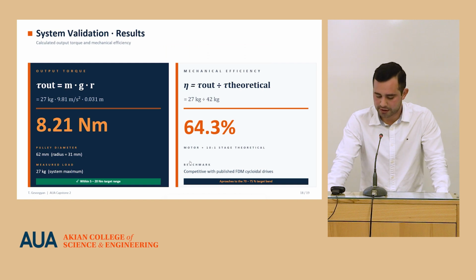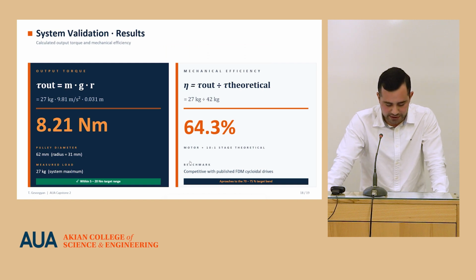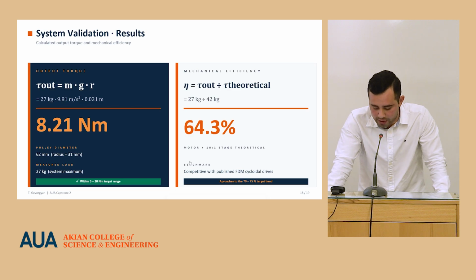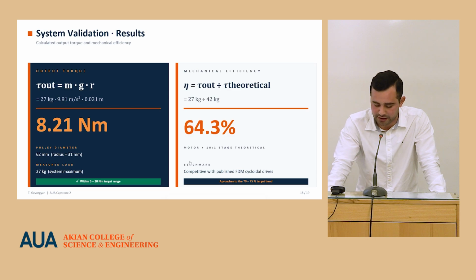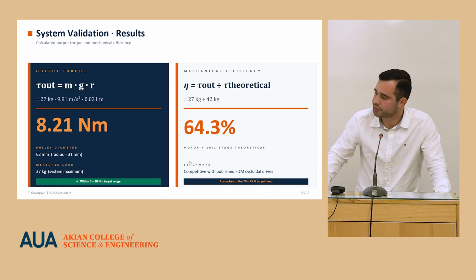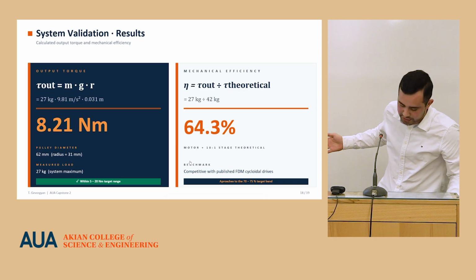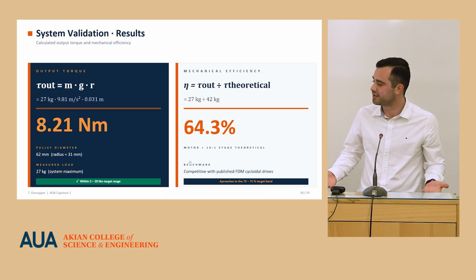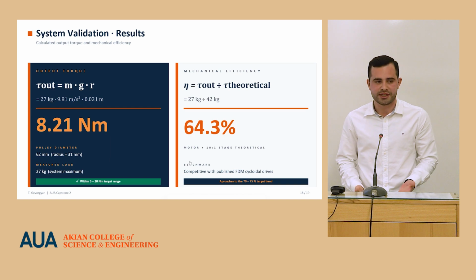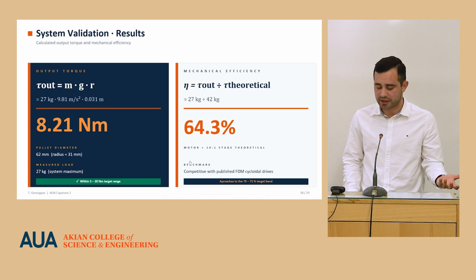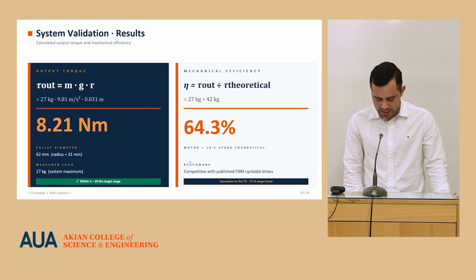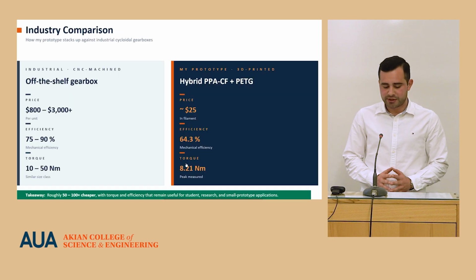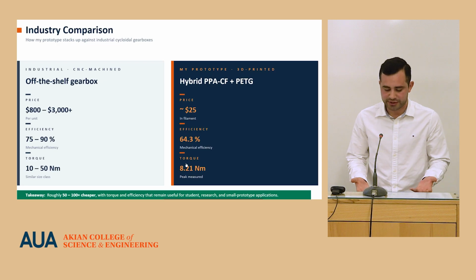And here are the calculations after this pulley test. My output torque was 8.21 Newton meters, which is within the range from 5 to 20 Newton meters, and my efficiency was 64%, which approaches the 70 to 75 target range. But I don't consider it a failure because 64% is really a good result too for a 3D printed gearbox. And here you can see a comparison between CNC machined and 3D printed cycloidal gearboxes.